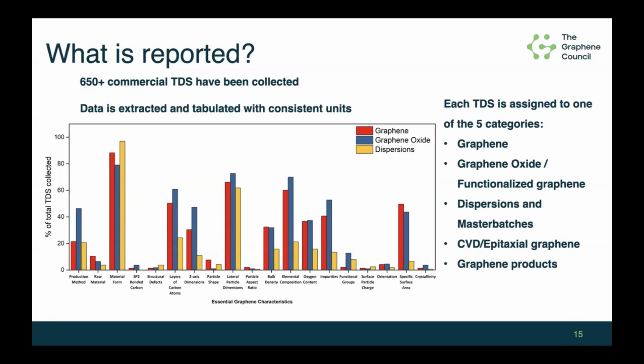Now, when we look at the total number of TDSs, we see that certain properties like the material form or the lateral particle dimensions are reported more often, almost more than 60%. But other key properties, for example, the ratio of the sp2 bonded carbons, the layers of the carbon atoms, the z-axis dimensions, the oxygen content, or even the surface particle size, are reported in less than 10% of the TDSs, and it is very critical to understand how these factors play an important role for your final application product.